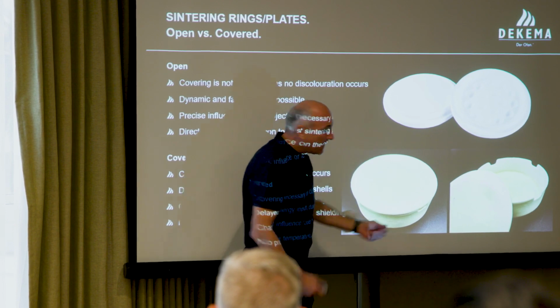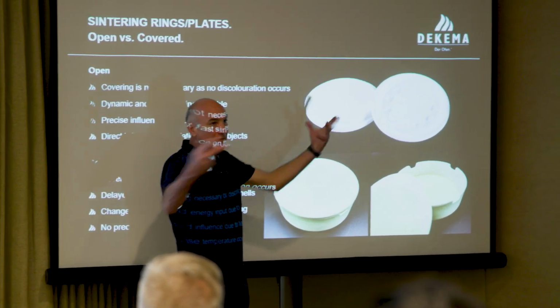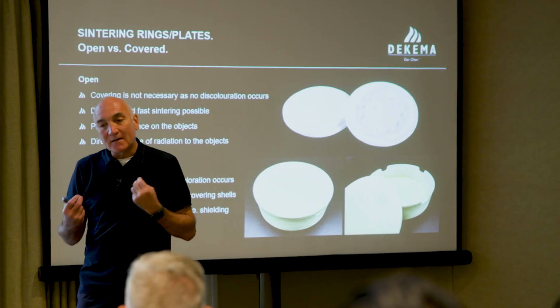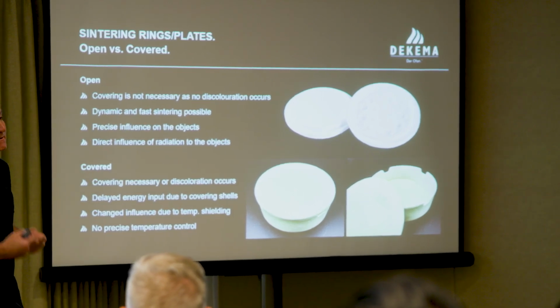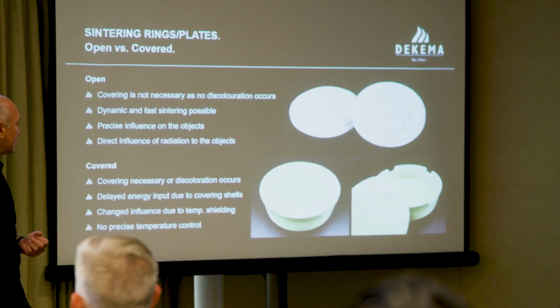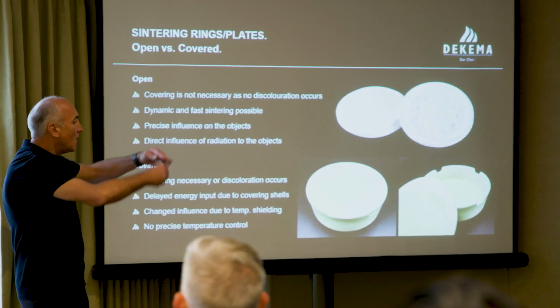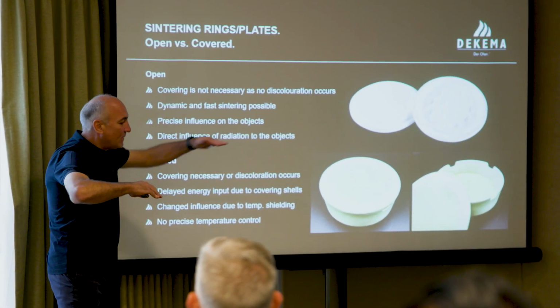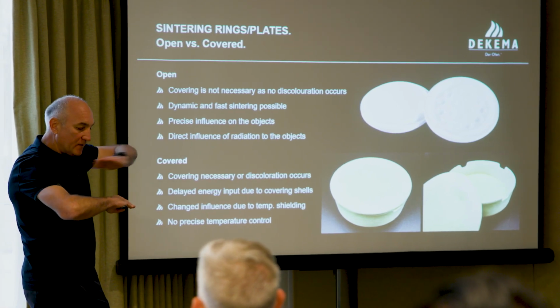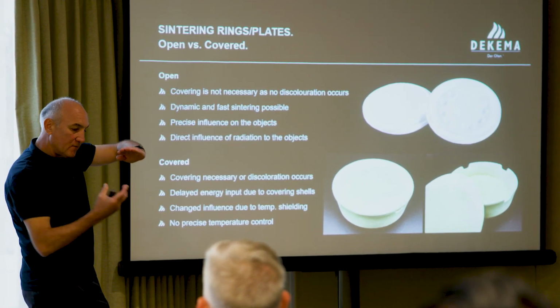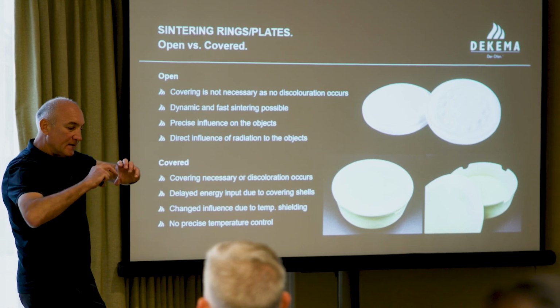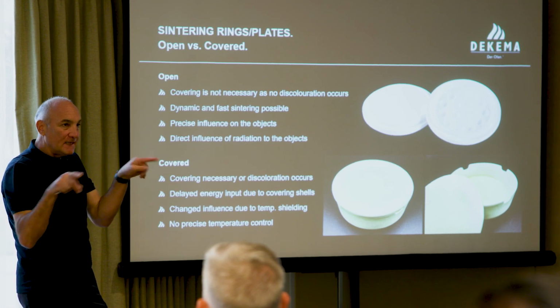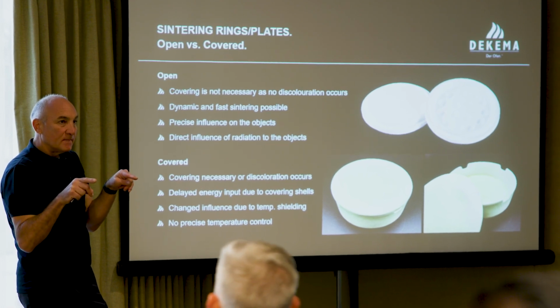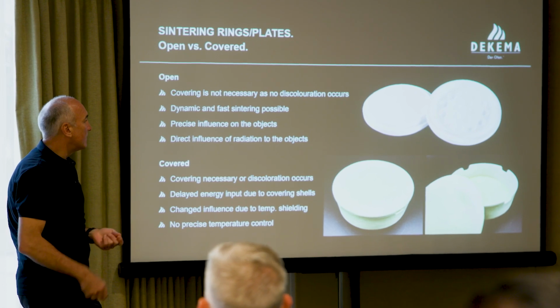You close it, you cannot sinter fast. As soon as you work like this and you have high heating rates, this will all explode, because these parts cannot withstand the high temperature changes, the high temperature. Yeah? That's why we have a patent on rings and plates, as we call them. So we have a horizontal and a vertical part. The ring is a vertical part, and the temperature expansion and shrinkage is fully independent. That's why we heat up so quickly with the right material.